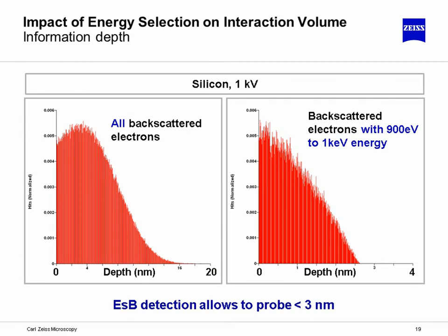A histogram showing the number of backscattered electrons as a function of their depth shows a maximum depth of 16 nanometers in the unfiltered case, in the case where we are detecting all backscattered electrons. Now, using the filtering grid and applying a potential of 900 volts, we can select the energy window between 900 electron volts and 1 kilo electron volt. And you can see now the information depth is below 2.5 nanometers. Therefore, ESB detection, energy selective backscatter detection, allows us to probe depths that are less than 3 nanometers.